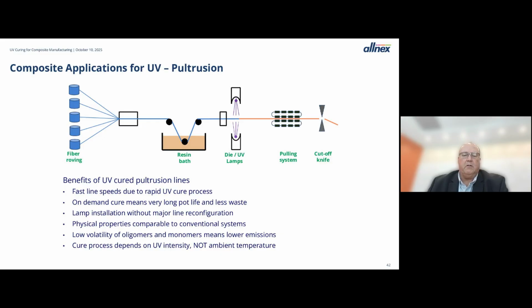Your line speed is going to go faster due to the rapid UV cure process. The pot life is going to be a lot longer. Physical properties are going to be comparable. And I didn't mention this before, but if you see a lot of variation over the course of a year on your plant floor, say you're operating in the northern part of the Americas or somewhere in the northern regions, where maybe out on the plant floor you see a big variation in temperature between winter and summer, that can have an effect on the quality and the pot life of your thermal systems. But because UV pretty much just depends on the UV intensity and UV energy, and not on ambient temperature, you don't see a lot of property variation if ambient temperature varies over the course of the year.